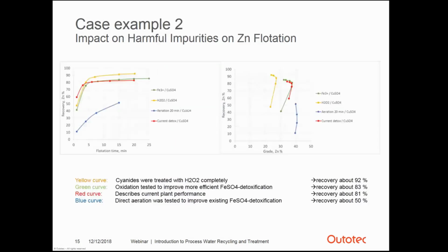Another case example here is from the study of a zinc flotation process, where some free cyanide affects flotation performance negatively. Cyanide complexes the copper used as activator for zinc. And in addition to that, cyanide itself has a depressive effect on sulfide minerals. The used detoxification method is the iron cyanide precipitation process, which is made with ferrous sulfate. However, it has been observed that the detox process is not working well because free cyanide is found to be present in flotation waters still.